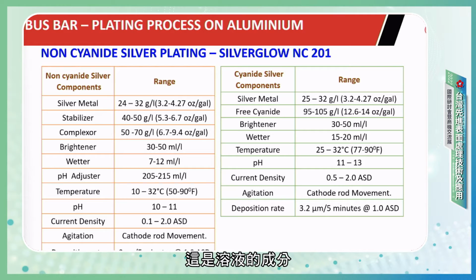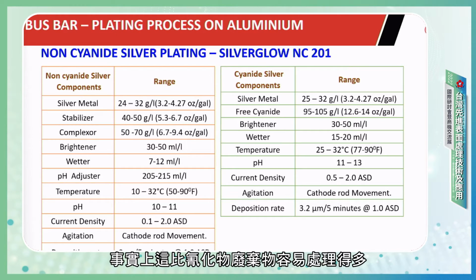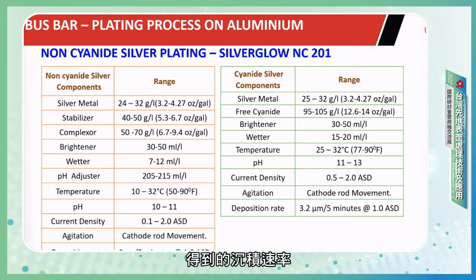This is the composition of the solution in comparison to the cyanide-based one. You can see that the metal works in more or less the similar range, so it doesn't create any additional burden in terms of waste treatment. In fact, it will be much easier than the cyanide-based waste treatments. We are getting approximately similar rate of deposition as that of cyanides, which is also good for the industry.